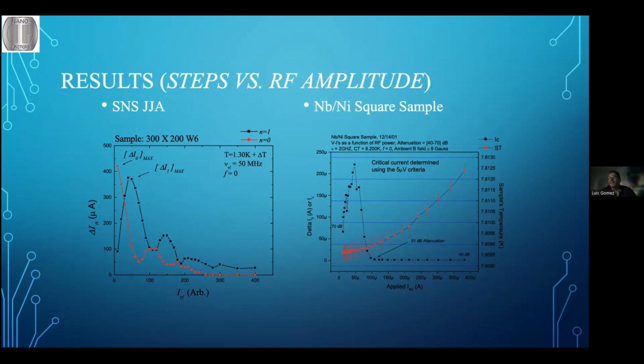Yes, that is what I have understood. Thank you. So you have an oscillating system that has a characteristic frequency. If you play with the values around the characteristic frequency, then you get the maximum response. If you go away from that characteristic frequency, then you don't see much change, even though you change many things in the system. So to be excited about the measurement, you place yourself right where the characteristic frequency of the system is. You make some changes, and in that way you can characterize the system.